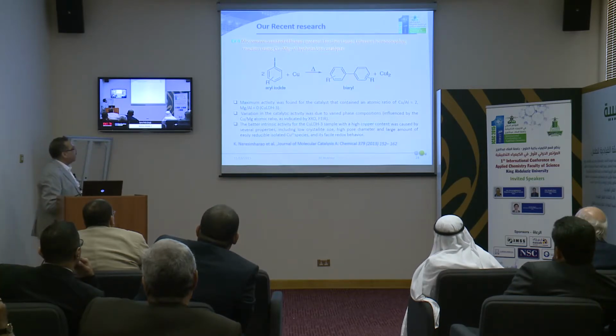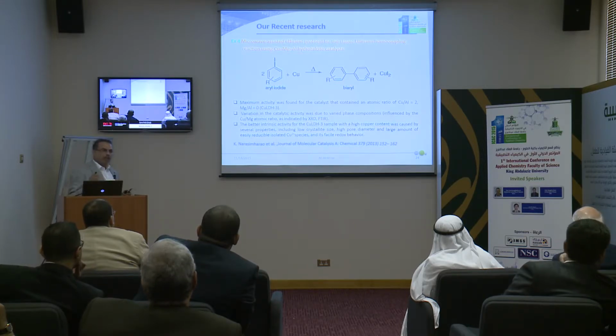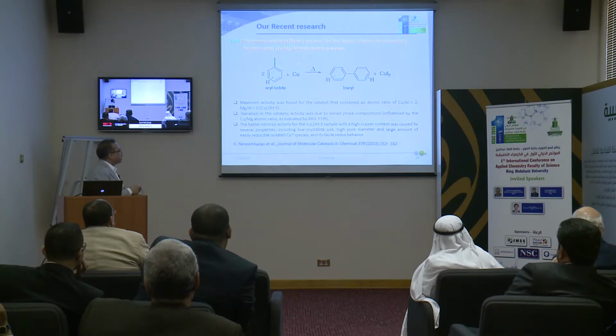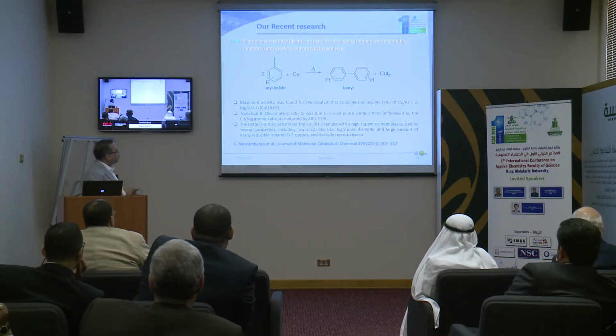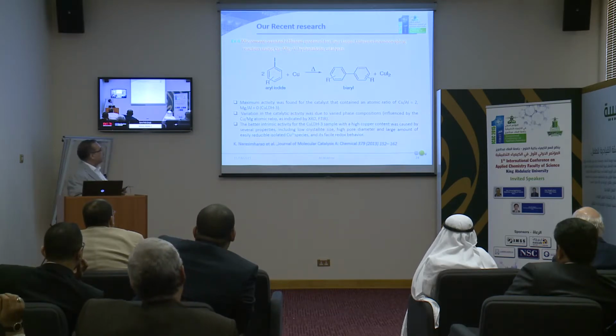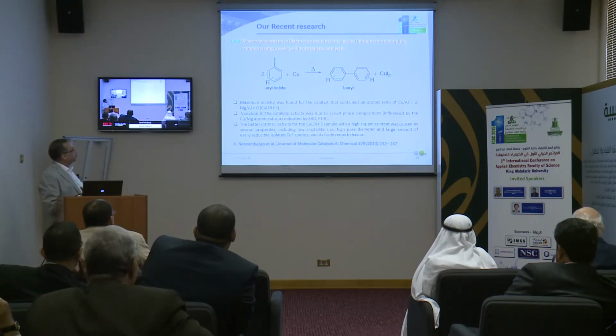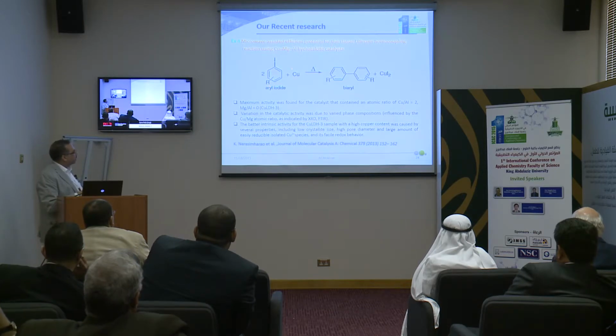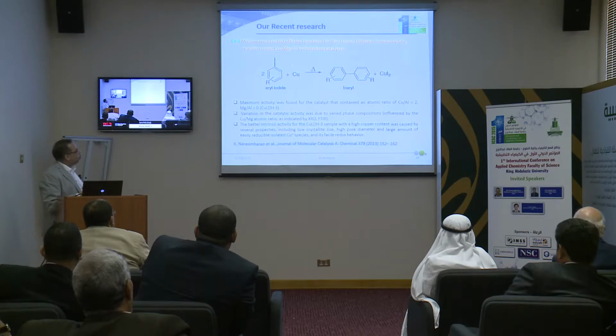In addition to that, there is nice work on CC coupling, which is important, like Suzuki coupling and Ullmann coupling, and homogeneous CC coupling by aryl formation. The literature uses complex copper material, and the copper should remove the iodide, forming cuprous iodide, cupric iodide at the end of the story. But replacing this catalyst, usually this catalyst needs base, needs complex, which can never be regenerated again.